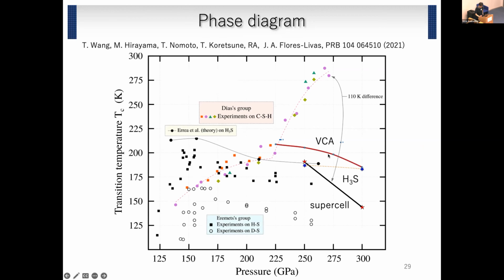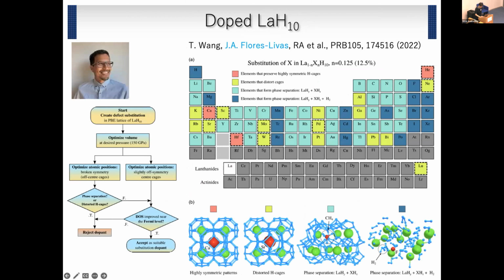And concerning the doping effect, we also studied the effect on LaH10. Jose again introduced many kinds of elements in the network of LaH10. And in many cases, the structure is destroyed. For example, if we put carbon, then immediately the cage is destroyed. But in the case of strontium or calcium, the cage still survives.